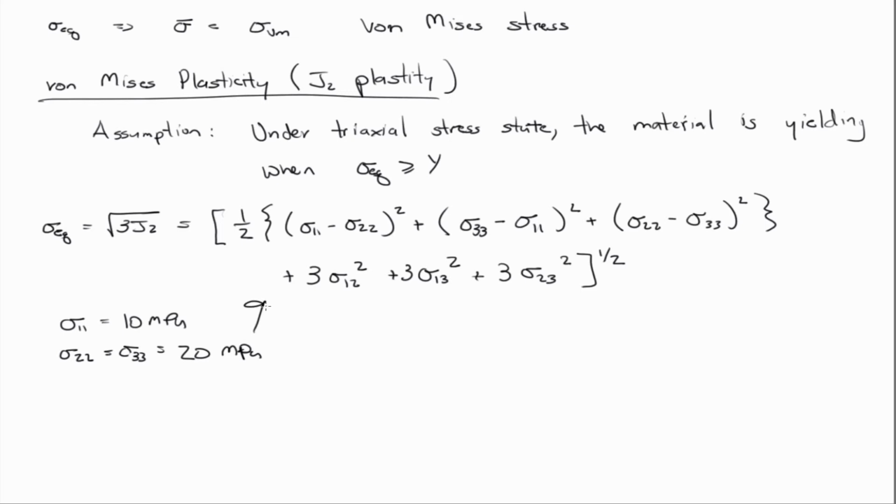We plug those guys in there and compute what the equivalent stress is going to be. It's going to be 10 megapascal. And our yield stress was 15, therefore not yielding in this case.